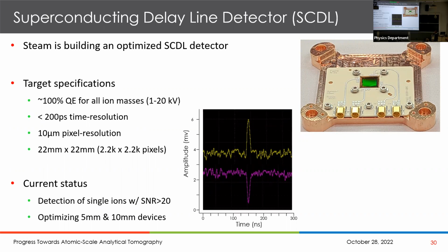With robust signal to noise and so on. This is quite important because I'll just say this briefly now. Atom probes use a conventional copper wire delay line that's significantly larger, up closer towards a millimeter in size, but the pixel size is a very large fraction of the detector. And the problem with that is that if you have two ions evaporate next to each other, they cannot be resolved as a single hit. So you get multi-hit losses.